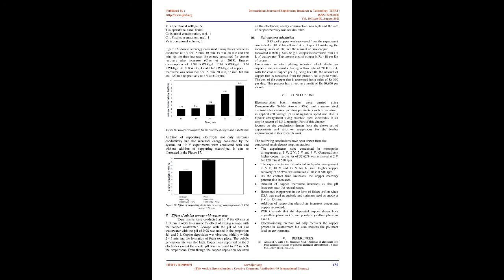In this aspect, quantitative analysis was done on stainless steel, which was used as cathode during electrowinning of copper at 2V for 120 minutes at 510 rpm. It is observed from the results presented in Table 4 that there was an increase of weight of 0.6006 grams on the cathode, indicating copper deposition has taken place on the cathode surface.